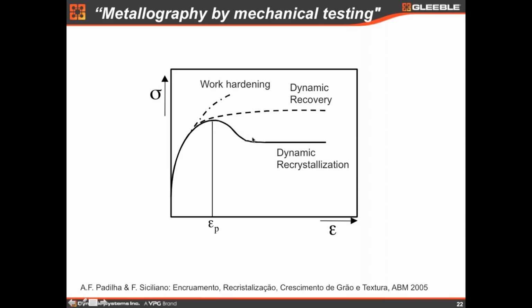So when you see a peak, then we see that there is dynamic recrystallization occurring in our experiment, and this decrease in stress is because there is a massive elimination of defects and dislocations. So the stress falls, and we see this peak and then a plateau. That's the steady state of dynamic recrystallization. And this is the peak strain and the critical strain. When dynamic recrystallization starts is somewhere here. So we can see that there's a departure from this curve of dynamic recovery. We call that metallography by mechanical testing, because we can associate what we see in the mechanical test with the microstructure and what's going on during the test.